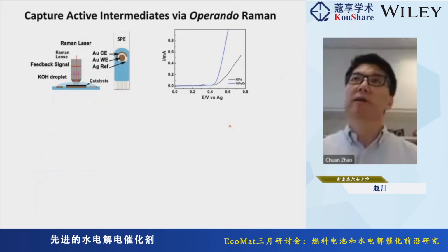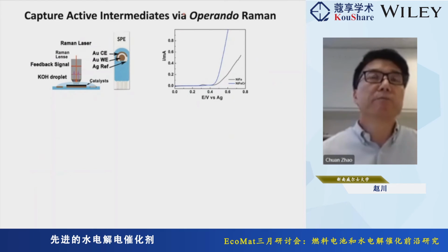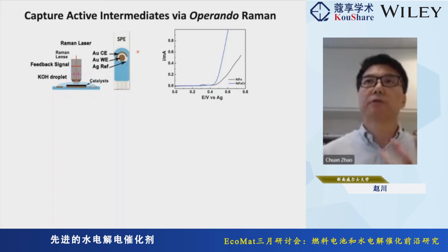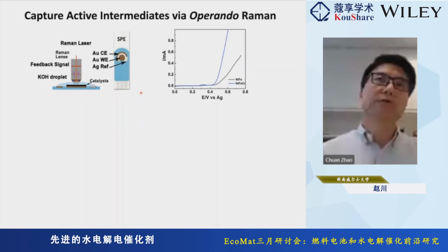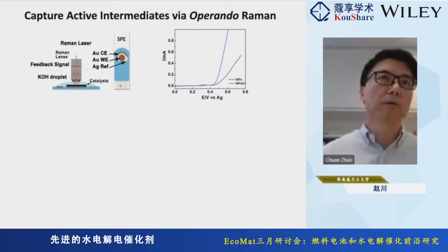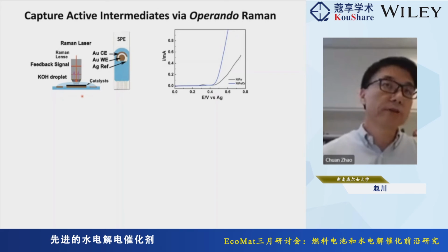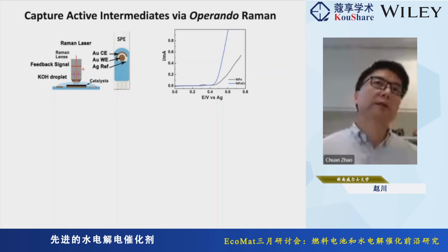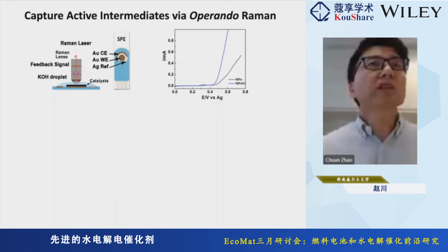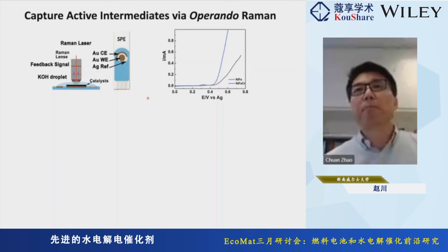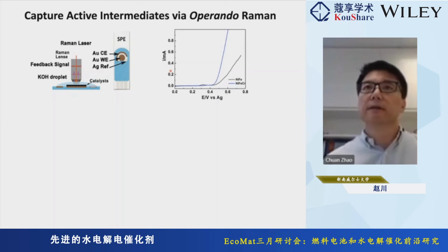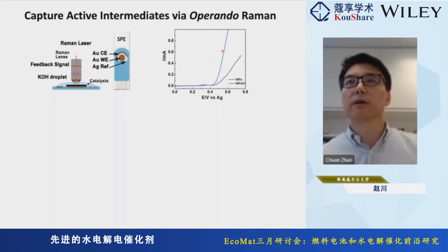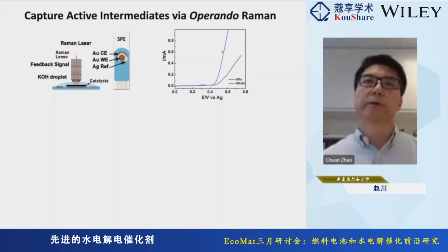Fortunately, this could be picked up by Raman. So we used a simple Raman cell to do this experimentally. What we use is a screen-printed electrode, which is commercially available, and then we add a drop of the KOH electrolyte, and then we immerse the Raman lens. So the laser hits the sample, and we can collect the signal. And we can run the polarization curve. We can still see on the surface of the working electrode that we get enhanced OER performance compared to nickel iron.